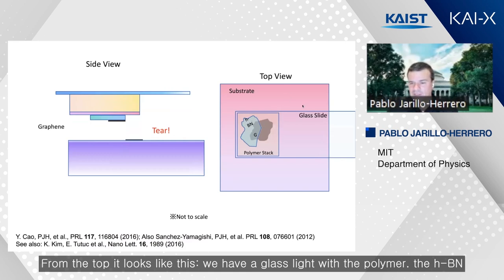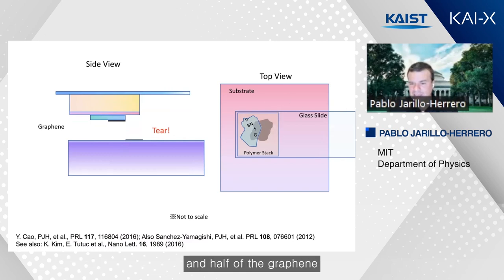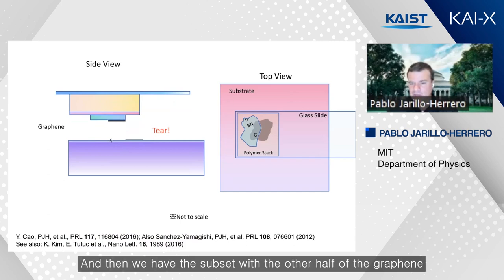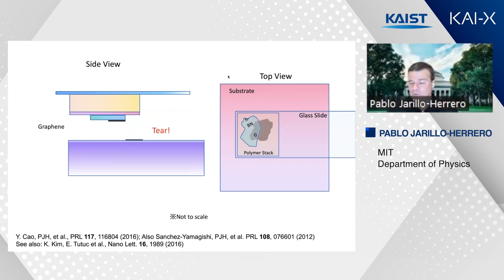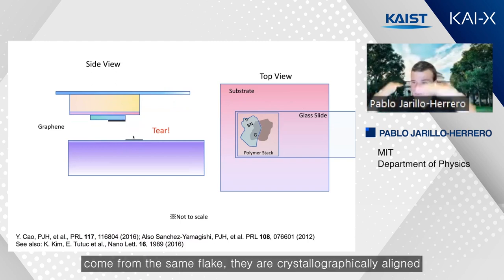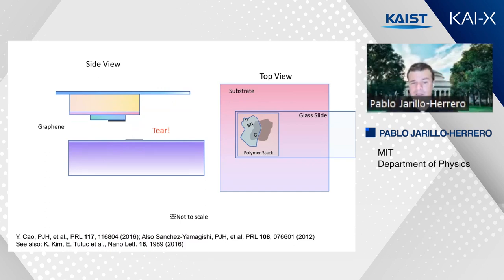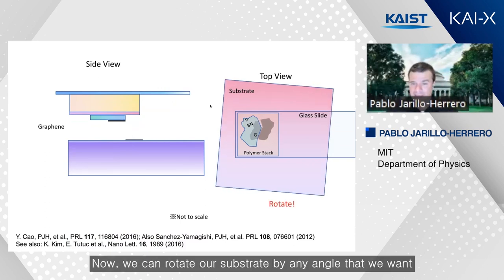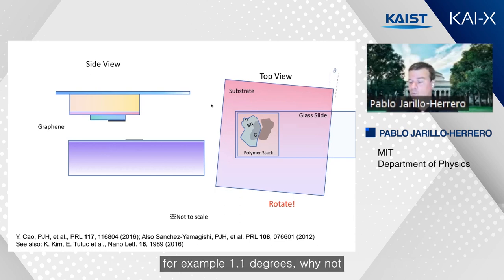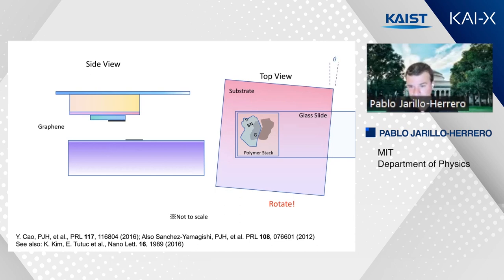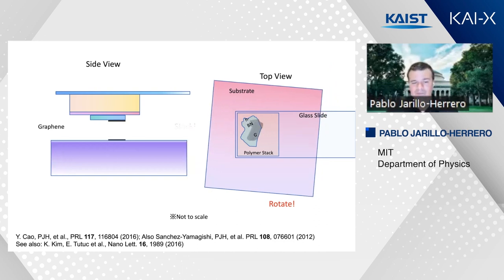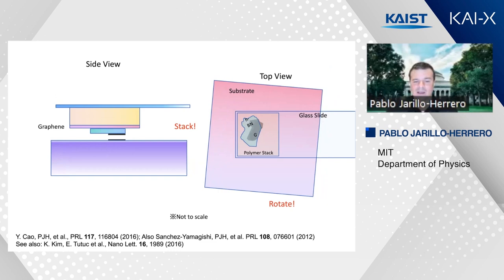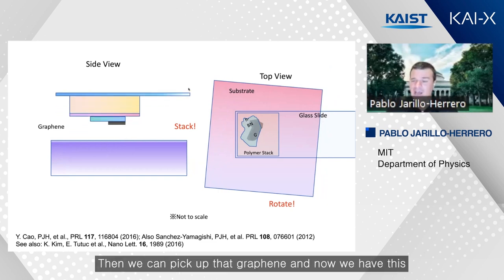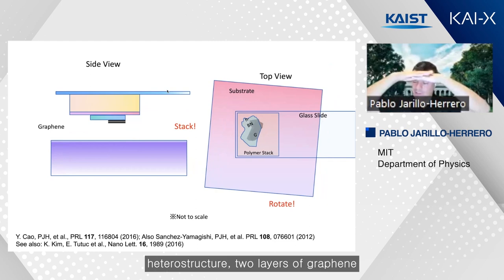From the top, it looks like this. We have a glass slide with the polymer, the HBN, and half of the graphene. And then we have the substrate with the other half of the graphene. Now, because these two halves come from the same flake, they're crystallographically aligned, even though they are at different heights. Now we can rotate our substrate by any angle that we want. For example, 1.1 degrees, why not? And then we can shift it on top and we can stack it. Then we can pick up that graphene. And now we have this heterostructure, two layers of graphene at that magic angle twisted, okay?